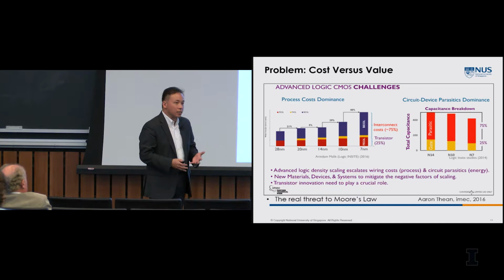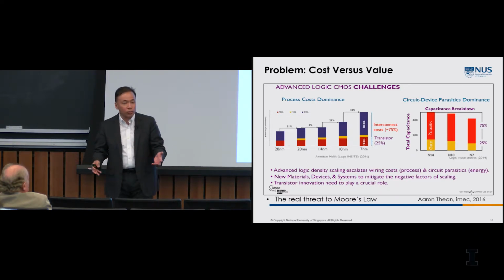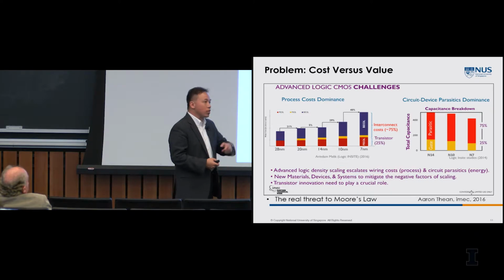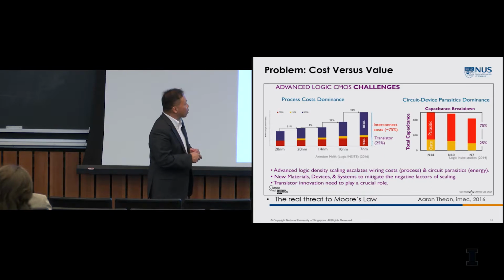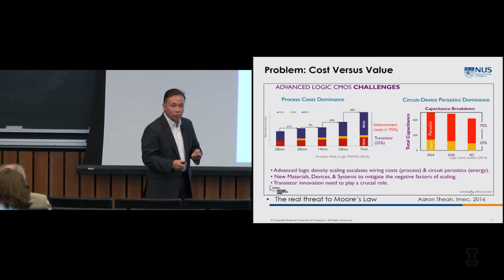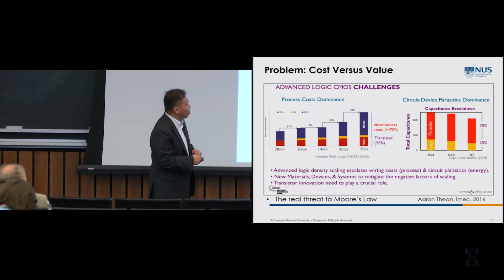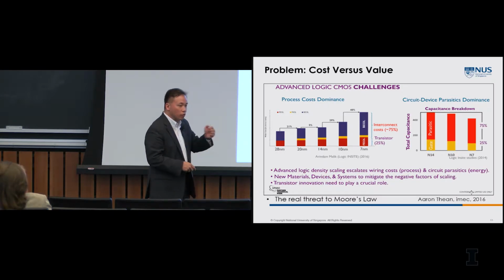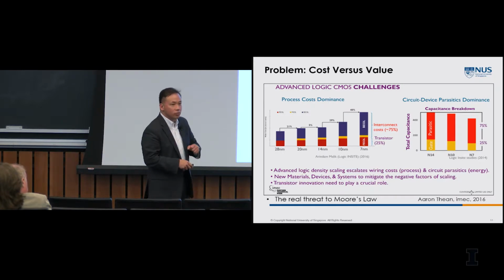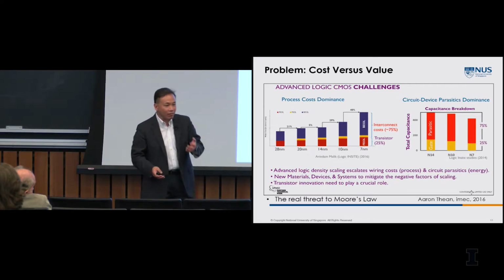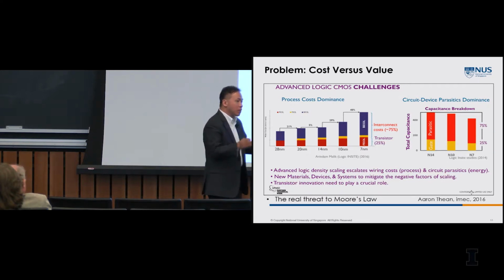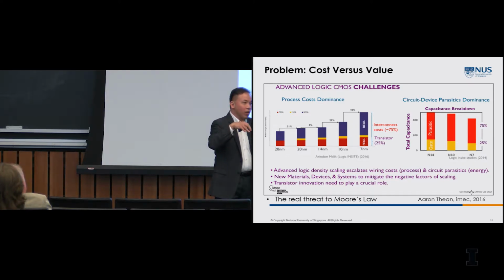Now, that increased wiring also creates another problem, and the problem is parasitics, right? Ultimately, we want to switch these circuits. We make them denser, but we want to switch them at lower energy and higher speed when we scale. If you look at the parasitics, which is really the load that slows down the switching, you can see that as a function of technology node, the gate capacitance, which is the switching of the gate itself, versus everything else, as you switch a transistor, everything else is also 75%. So effectively, you're wasting all your energy switching something else whenever you're switching that transistor, and that something else is all that wire that is coming down like a forest of vines connecting to your transistor.